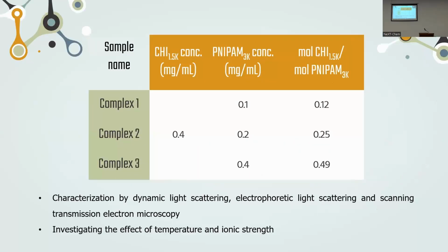For the preparation of these complexes, we mixed both components, keeping the chitosan concentration constant, and we varied the PNIPAM concentration, so we obtained 3 different complexes. After 24 hours, the complexes were characterized by dynamic light scattering, electrophoretic light scattering, and scanning transmission electron microscopy. And we also investigated the effect of temperature and the ionic strength.